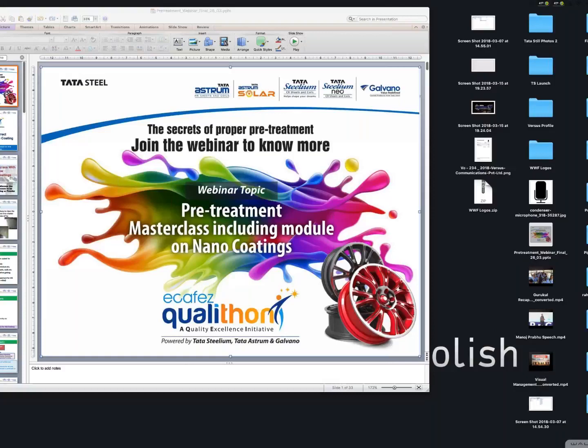Mr. Vipin Pathak is asking, is the result for xenon arc test treating CRMS same in the tricationic phosphating or nanophosphating? Actually, xenon arc test and treatment of CR and MS, probably there's no direct relation there of phosphating and nano coating, because xenon will attack only the top coat, not even your primer. So this is way below primer. So I don't think that should give you any adverse effect as such with xenon arc.